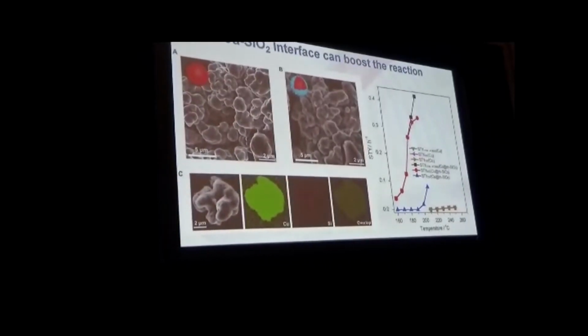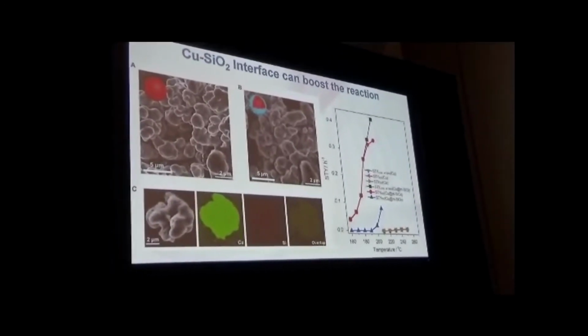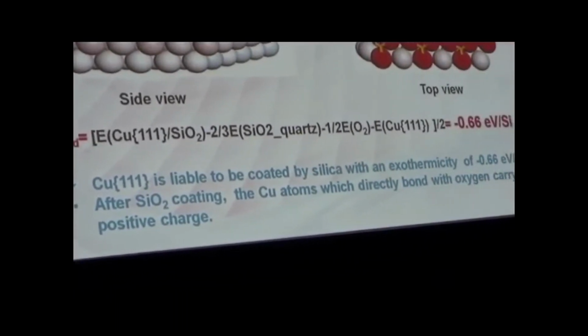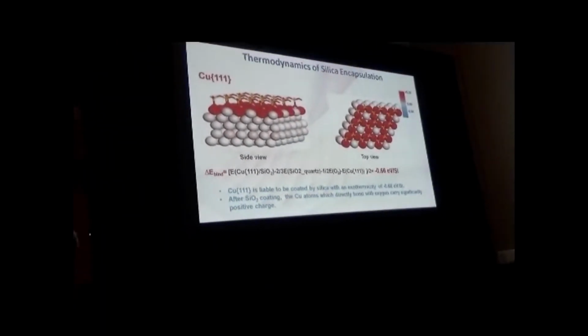Okay. When we use the copper alone, the copper reactivity is very low. When we couple the copper with silica, the reactivity is increased sharply. So it's the interface effect rather than the nano effect. Here is the model. Why? Because the silica can match very well with the copper. The estimated binding energy is about minus 0.66 eV per silicon, so it's much more stable. And the silica can stabilize the copper 1 plus.